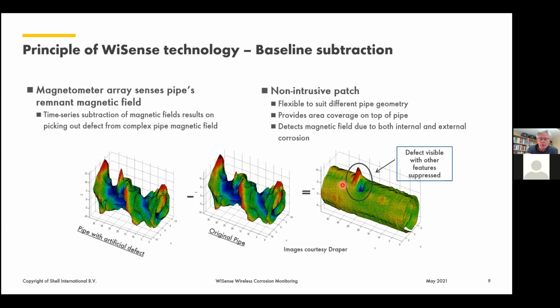We talk about a permanent sensing system. Why is that important? Well, if you look at the middle figure, this is the magnetic field around the pipe, and it's a seamless pipe. And you see that it's quite an irregular magnetic field already, being measurable outside the pipe. And it's not so easy to detect a defect. In fact, this was a test condition where we could add and remove a defect a bit artificially. But here is the same background pattern with the defect indication.